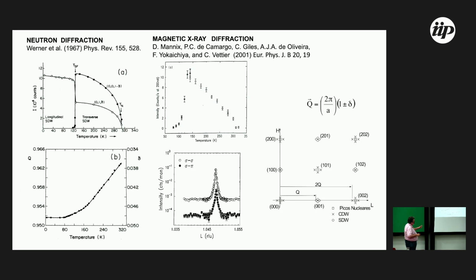Okay? So this is a map of the reciprocal space. Because chromium is BCC, there is no diffraction at the 001 position, because of the structure factor. However, we observe the satellites around the 001. And around the 002, we observe the charge density wave. It is a 2Q, double the size of the spin density wave of chromium. But the antiferromagnetic properties of chromium reflect bulk properties.